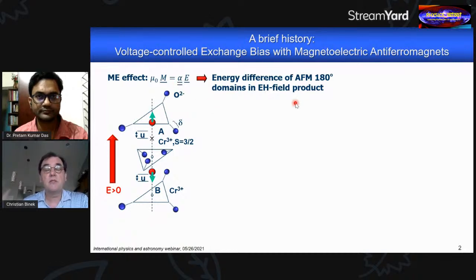Now it turns out that you can have 2 distinct 180-degree domains of this chromia. One is where the spins are down, up, down, up, down, up. And the other one is where the spins are up, down, up, down, up, down. And these different domains have different signs in alpha, and therefore different signs in magnetization response on an electric field, and therefore different potential or Zeeman energies in an applied magnetic field.